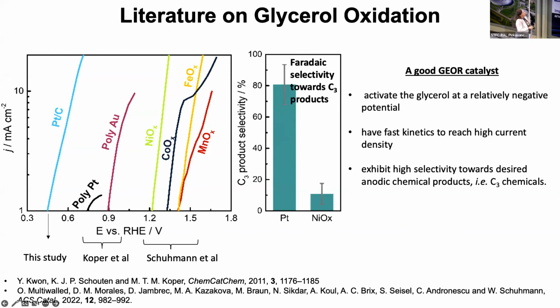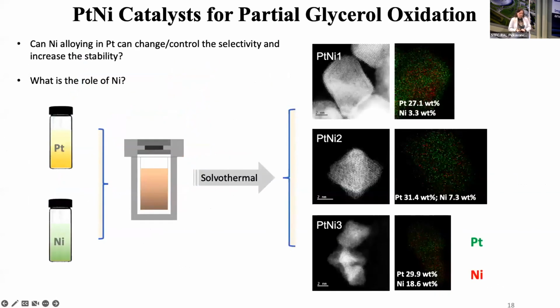So the question is, there is not much known on the glycerol oxidation. So we were wondering, why are these metal oxides so bad? And is platinum really so good? What is the selectivity here? So what we did, as I said, I normally work with carbon, but here we've supported all this on carbon, but that's about it. We took platinum and nickel, and we did a solvothermal reaction, and we varied the amount of nickel that we put on this platinum catalyst. So we had platinum with less nickel, platinum with equal amount of nickel, and platinum with excess of nickel.